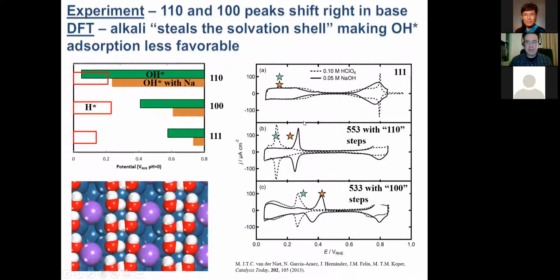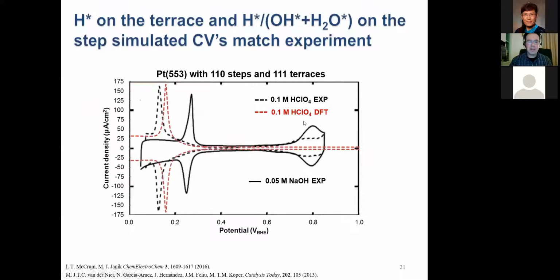And we've been able to compare that with detailed surface science experiments. We can then simulate these. So the black is the experiment. Now, we get the height and the position pretty much correct by looking at that as an exchange reaction using DFT for H and OH. And we did it again for the 100 surface as well.